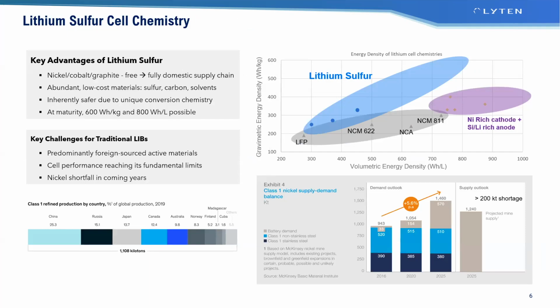And why lithium sulfur? So lithium sulfur, I think the first paper we saw with people trying to make a lithium sulfur cell, 1960s, okay? Like all great electrochemistry. People tried this, and they found it was very difficult, because the reality is, although the chemistry is very, very appealing, and the theoretical energy densities are very high, this chemistry is different from conventional lithium ion. Conventional lithium ion, you see the rocking chair, the intercalation chemistry, the lithium kind of inserts itself into crystal structures. Lithium sulfur is different.